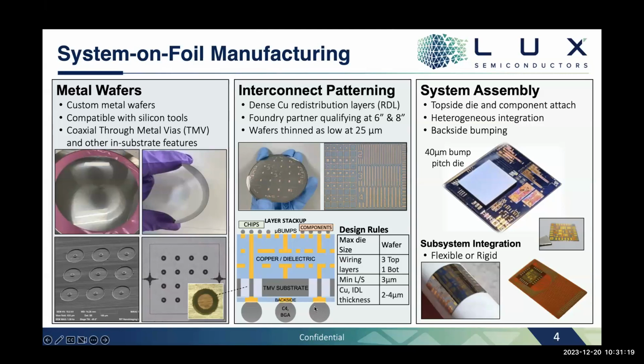So yes, you can bump either C4 or BGA on the backside, and we would just drill a hole that is equivalent to the diameter of whatever bump you're going to place on the backside. That's very interesting. Let's say you had to put the C4, like a 130 micron pitch, which is the industry standard now, or a 1 millimeter BGA pitch. If you're removing that substrate to reduce the capacitance, would you still be left with any substrate if you're putting a fine pitch C4 or BGAs?